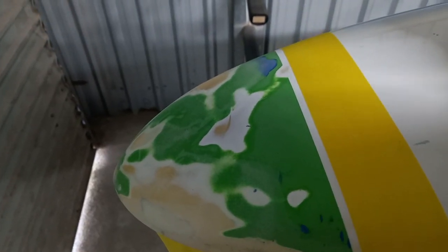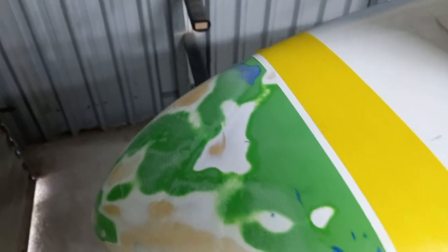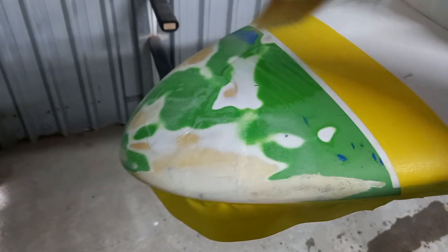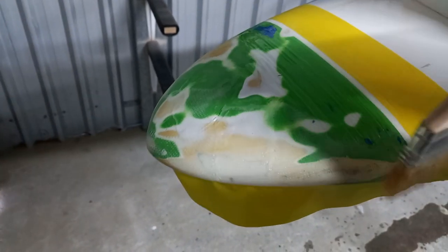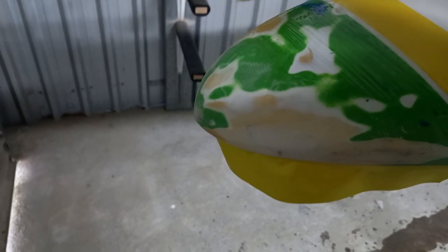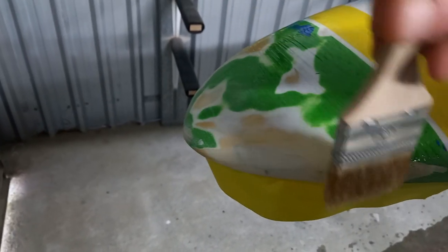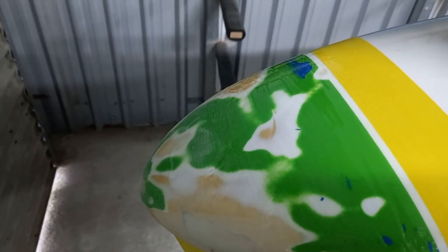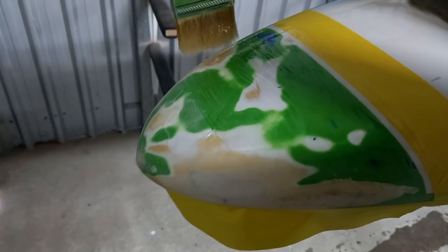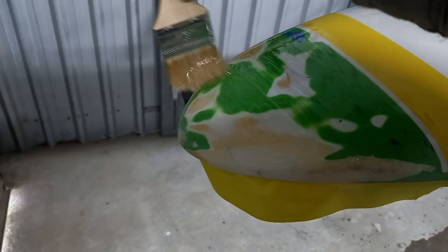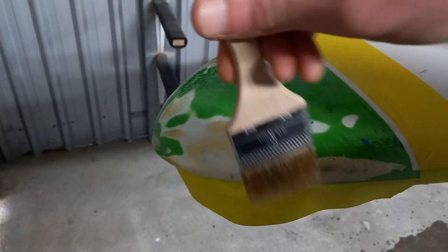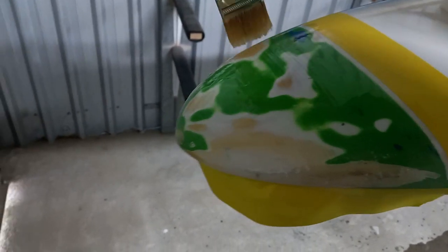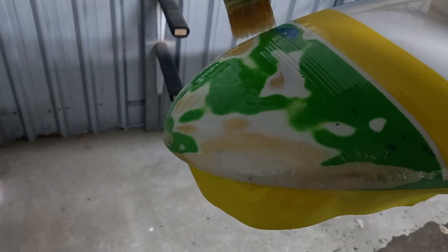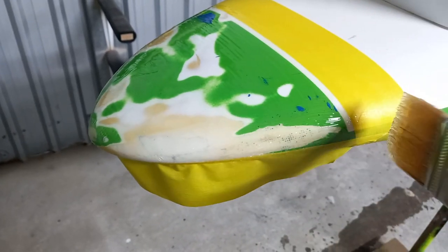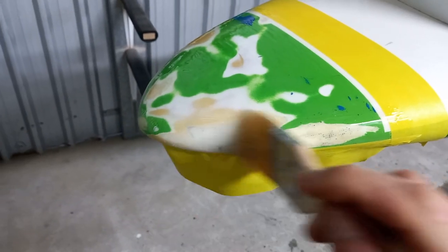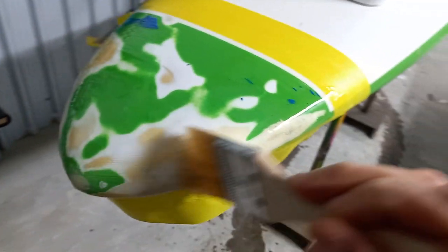For lack of better terminology, we're going to refer to this as the hot coating stage. So I've cleaned this up with just an air compressor and a towel. A lot of people will suggest that you clean up before your hot coat with acetone. I personally use Entropy CLR resin, and I find that this resin in particular, not others like Kinetics, seems to react really poorly if you clean the surface with acetone, and I end up with fish eyes and other blemishes. So if you're using this same kind of resin and you're having problems with blemishes, try not cleaning with acetone.